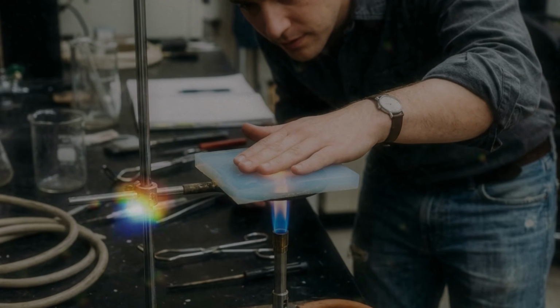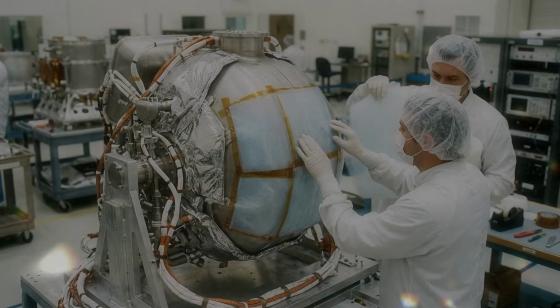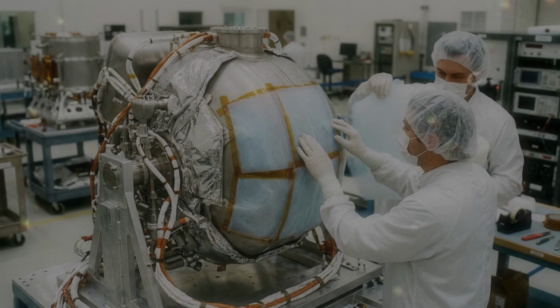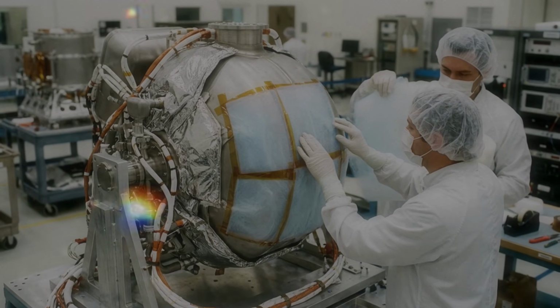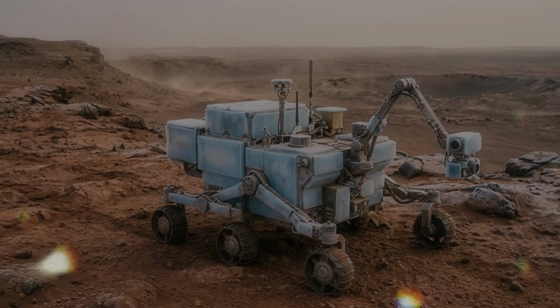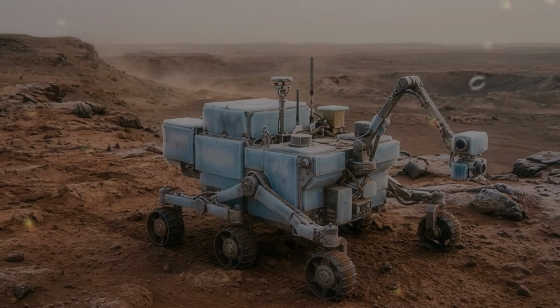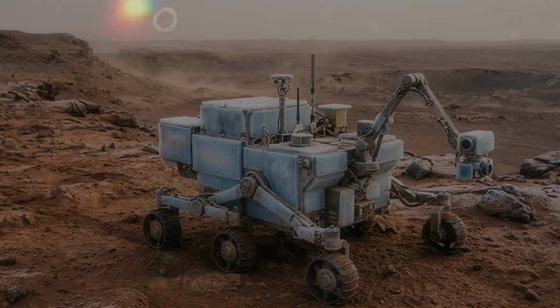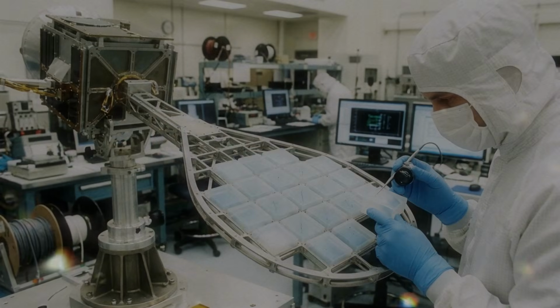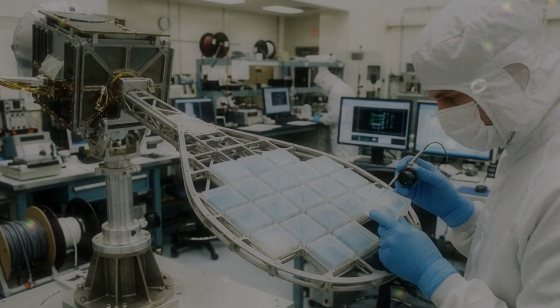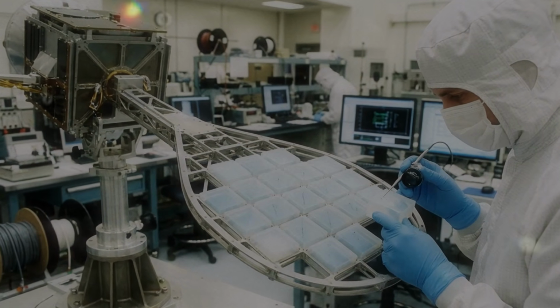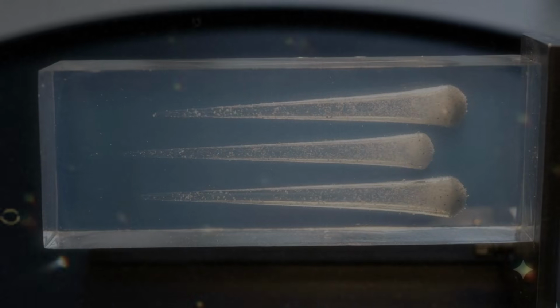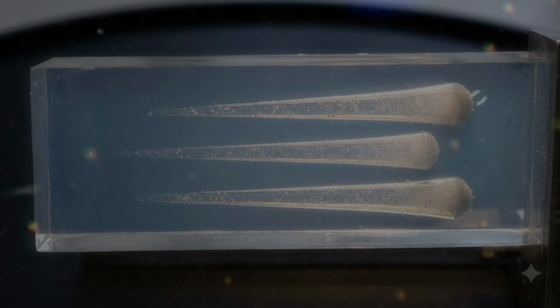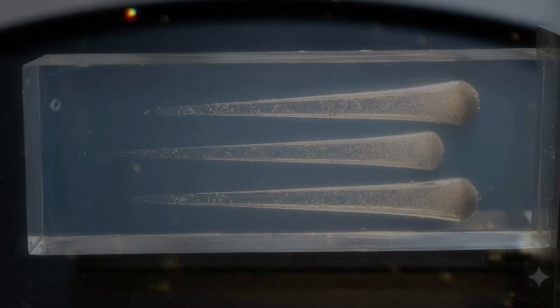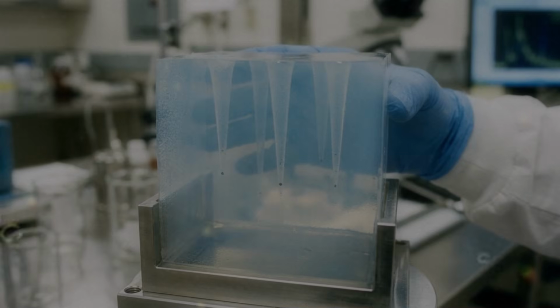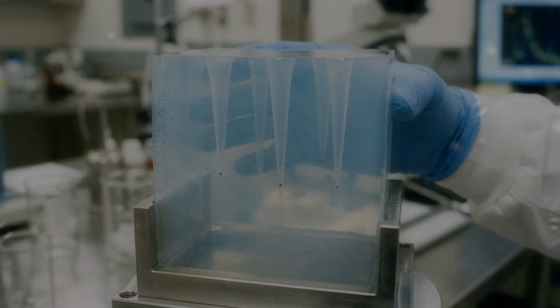Brittleness is not a necessary property of every aerogel. Researchers can reinforce the structure with fibers or polymers. Some polymer aerogels are flexible. Certain carbon and graphene-based aerogels can be compressed and then recover much of their shape. Others are designed to withstand repeated squeezing. The behavior depends on the strength of the solid framework and the geometry of the pores. A structure made from tiny rigid particles may break when bent. A structure made from flexible sheets may buckle and unfold. A network with carefully arranged cells can distribute pressure more effectively than a random fragile web.